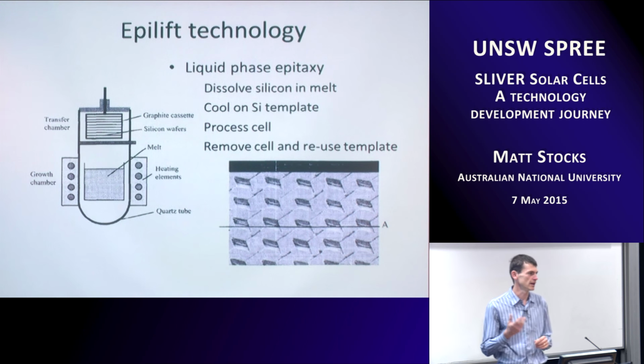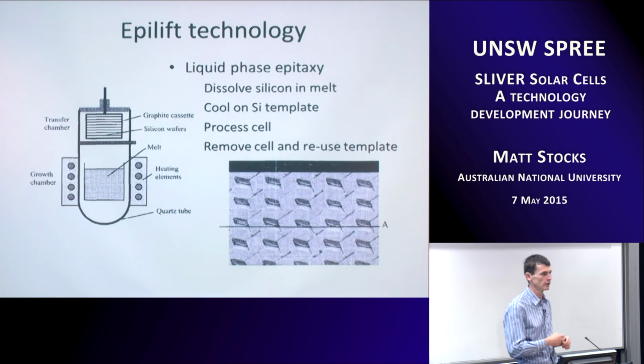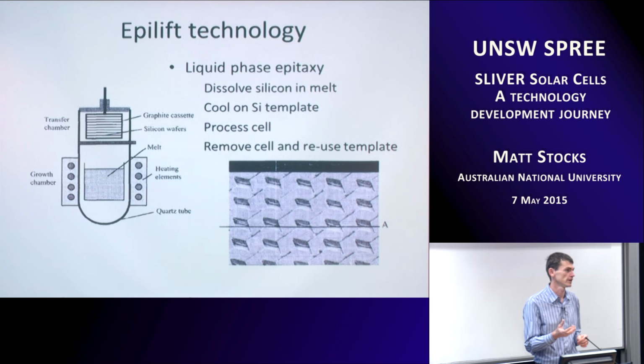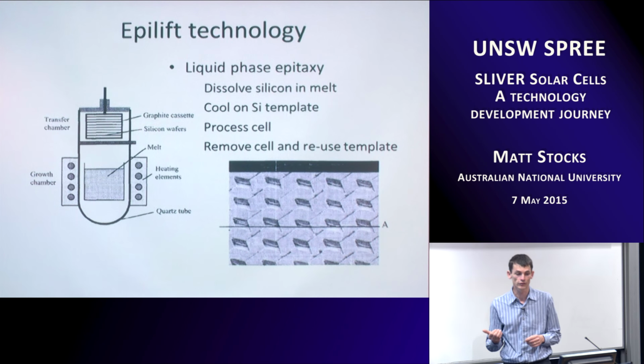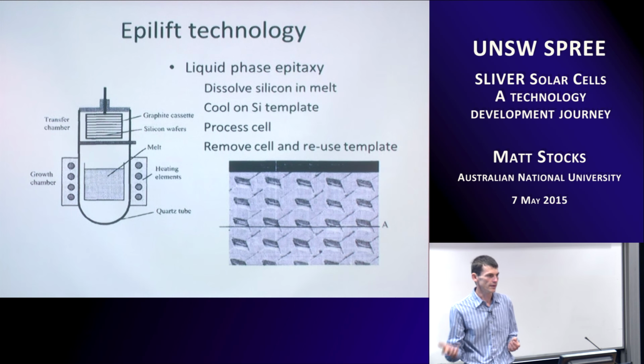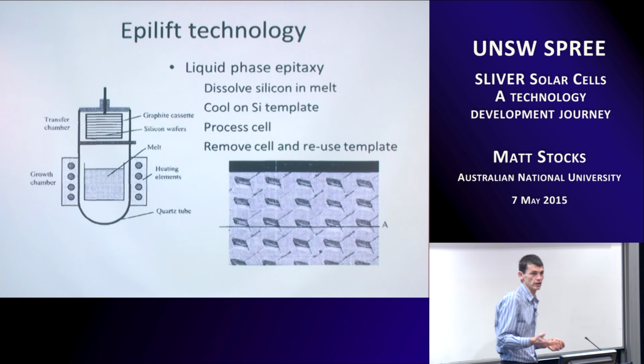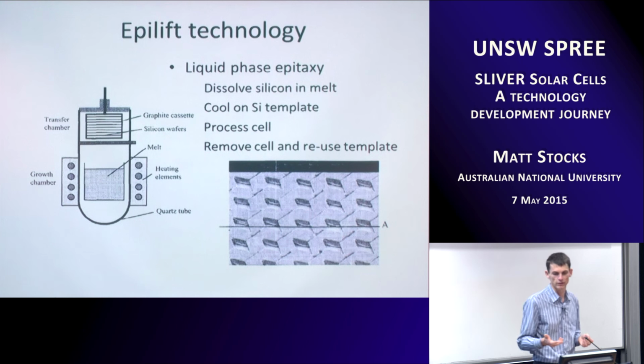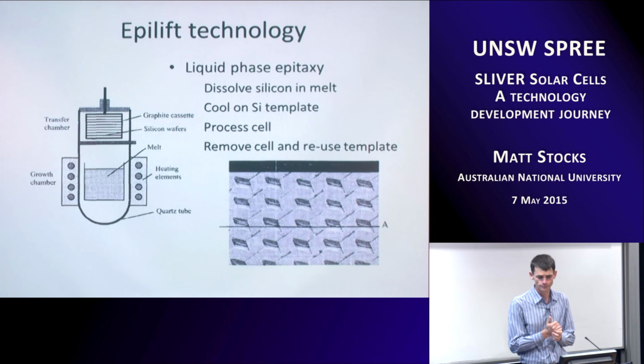So basically taking a metal melt, dissolve your silicon in that metal melt, you transfer that metal on top of your silicon, you cool the melt down, the silicon crystallizes out on the top surface of the silicon, we make our solar cell on that top layer, and then we remove that top layer and reuse the substrate. And that was the basic concept that was involved.